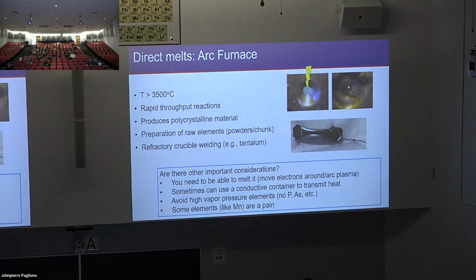All right, so arc furnace, what do we get? We get high temperatures. We get rapid throughput reactions because this is so easy. It lets us look at a lot of the chemical phase space. But it tends to produce polycrystalline material because it's such a fast process. The nucleation happens everywhere all at once, and you have no control over that. But sometimes crystals will form large enough grains that you can actually cleave off pieces. And if you want to make a measurement on a very small sample, you effectively have a single crystal.